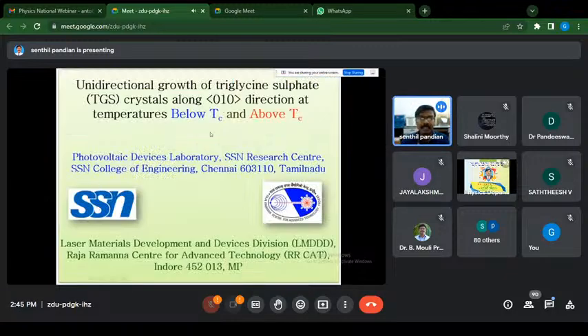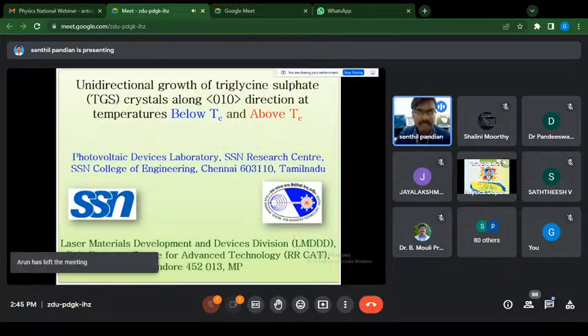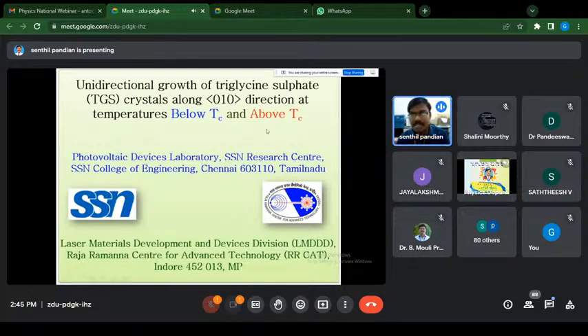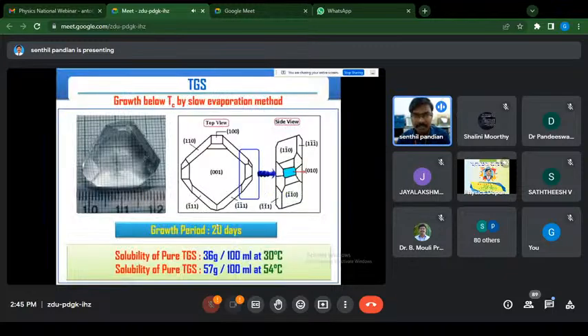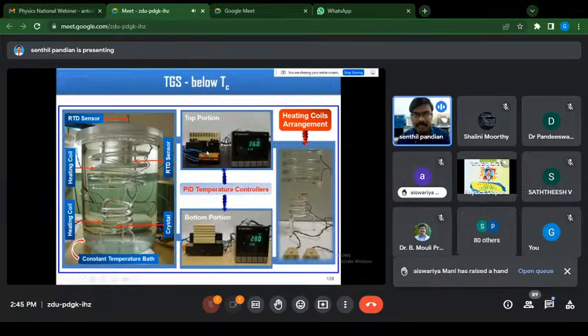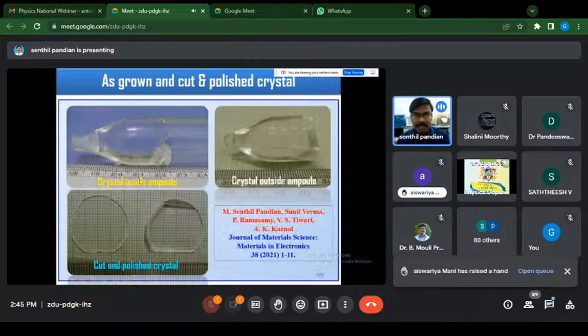And then this is the TGS, triglycine sulfate single crystal, with its phase transition point at 49 degrees Celsius. Below this temperature, the crystal belongs to the ferroelectric phase. Above this TC, the crystal belongs to the paraelectric phase, and we have successfully grown the crystal both below and above TC. So this is the conventional growth, and this is the polar b direction. We have selected 36 degrees Celsius at the top portion and 28 at the bottom portion. This is the heating coil arrangement we have done in RRCAT, Indore.